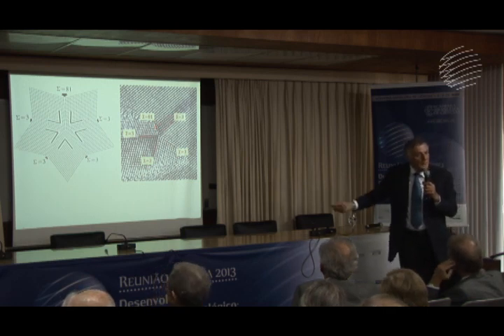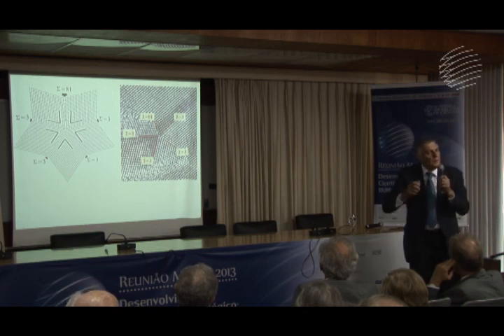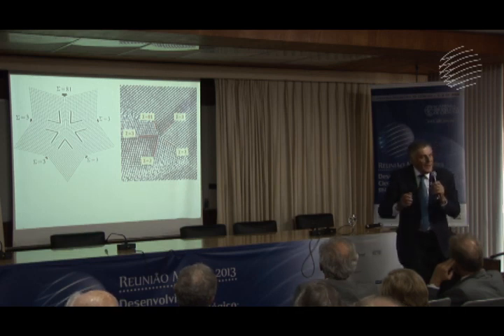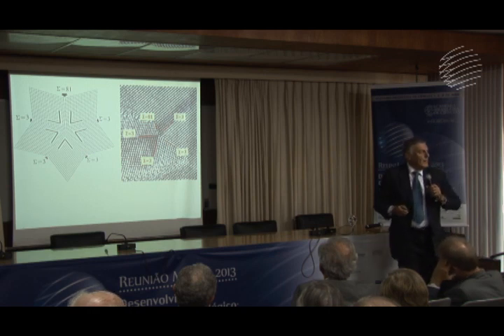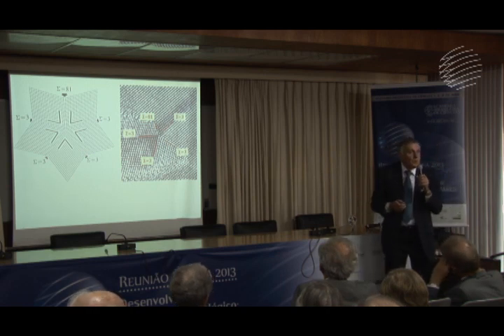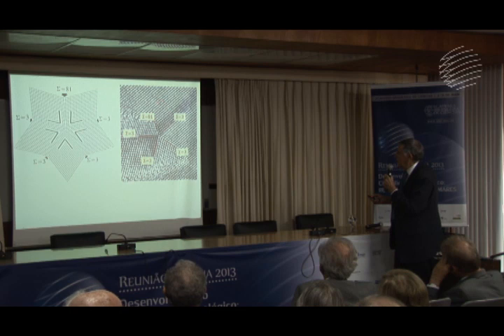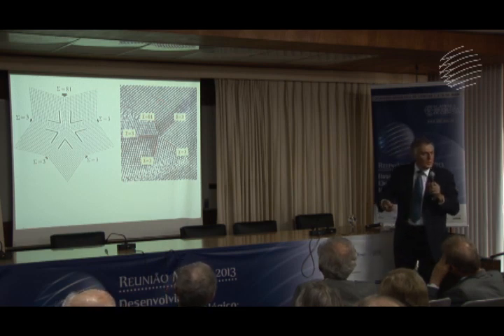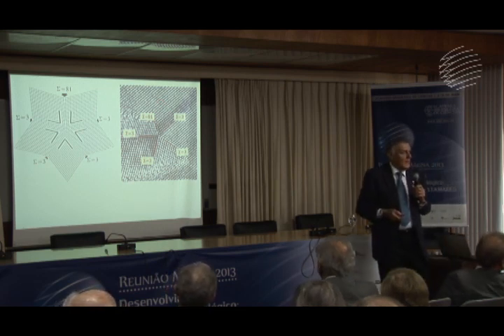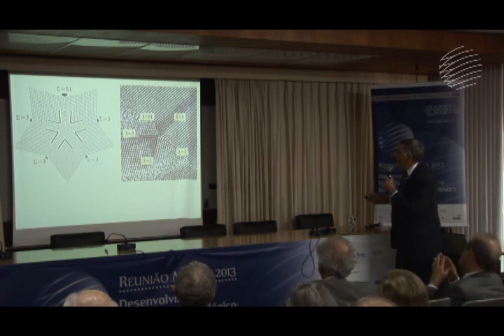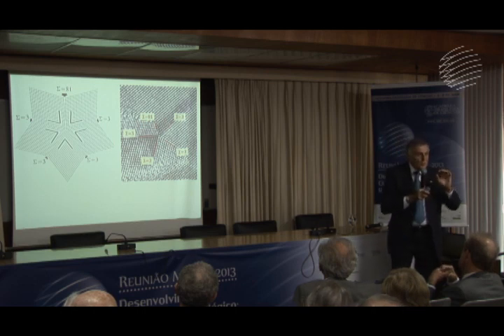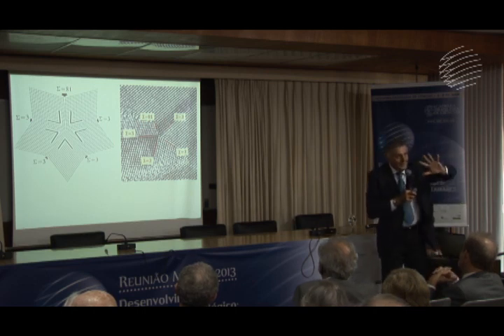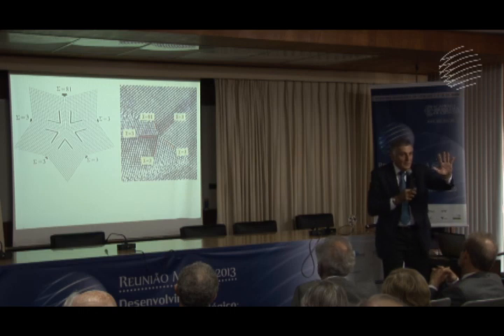What we have here are five twins. These are five different crystals, five different orientations. Now, if you take a diffraction pattern from just one of them, like this one here, you'll get a periodic, nice diffraction pattern. But if you take a diffraction pattern from all of them together, then you will have five superimposed diffraction patterns. 1, 2, 3, 4, 5, 72 degrees from each other. Why 72? 360 divided by 5.